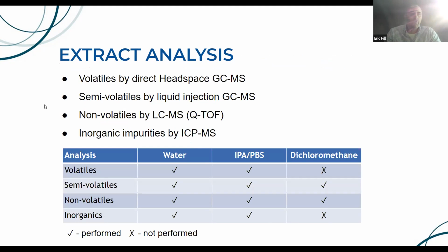We analyzed the extracts: volatiles by direct headspace GCMS, semi-volatiles by liquid injection GCMS, non-volatiles by LCMS, inorganic impurities by ICP-MS. And we analyzed all of the extract solutions, water, IPA PBS, and dichloromethane, with the exception that we did not analyze the dichloromethane for volatiles nor for inorganics. That was really due to the fact that, first of all, we don't expect to have any inorganics being extracted by dichloromethane. And also dichloromethane is extremely volatile and produces a very large interfering peak in the volatiles analysis and really renders that analysis kind of null and void.